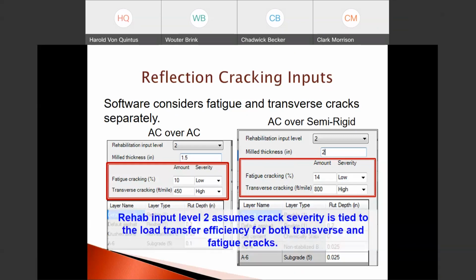The reason the severity level is entered is rehab input level 2 assumes that the crack severity is tied to the load transfer efficiency of both transverse and fatigue cracks. In other words, we wouldn't have any FWD deflection data to measure the load transfer efficiency. So in this case, the crack severity in terms of the pavement ME global values are tied directly to crack severity.